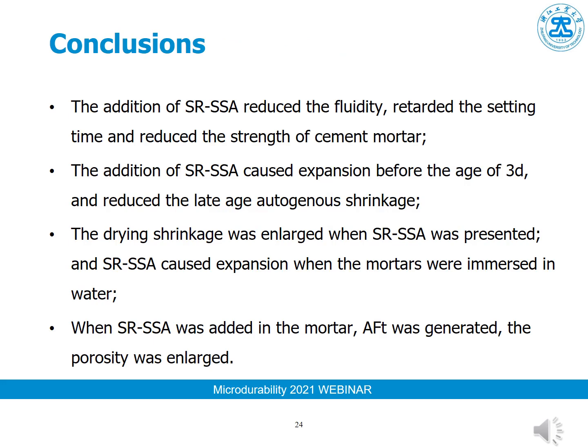Here we come to the conclusions. So the addition of the sewage sludge ash reduces the fluidity, retards the setting times, and reduces the strength of the cement mortar. And the addition of this ash caused expansion before the age of 3 days during the autogenous shrinkage tests and reduced the late age autogenous shrinkage. The drying shrinkage was enlarged when sewage sludge ash was present, and it caused expansion when the mortars were immersed in water. And when this ash was added in the cement paste, ettringite was generated and the porosity was enlarged. So these are the reasons for the change of the micro properties of the cement mortar with sewage sludge ash.